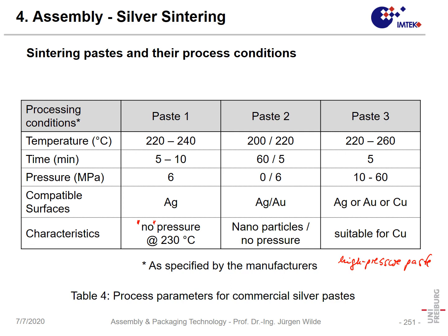And here again we have a similar temperature range, similar short times, but the pressure here can go up to 60 megapascal. Unfortunately, not all substrates will survive such a high pressure. On the other hand, here you can get very high strength of the die attachment after the bonding.